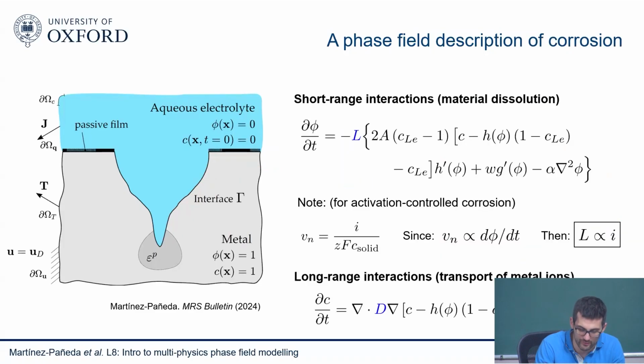So what do you do then? You have corrosion. So I'm going to bring mechanics, I'm going to bring other things into the picture, but I want to bring them progressively. So if I think of the simplest problem of corrosion, you have basically two variables that you need to solve for, or two equations. One is the transport of metal ions that I was discussing before. This is what I'm solving here. So it's a kind of Fick's law type of equation, a transport equation.